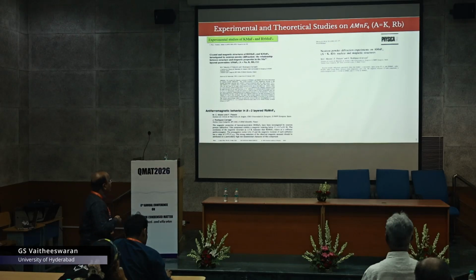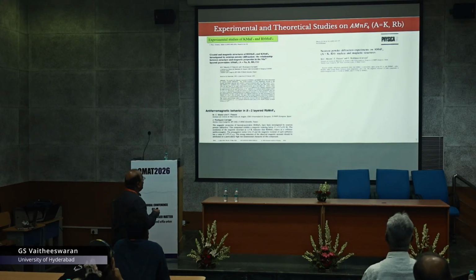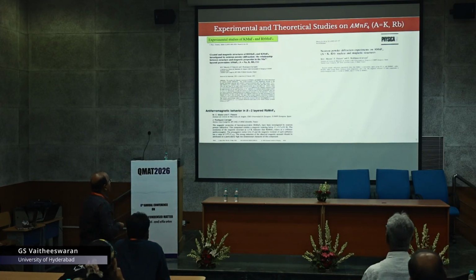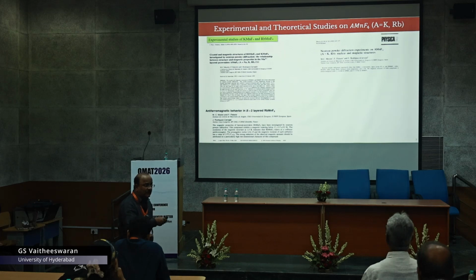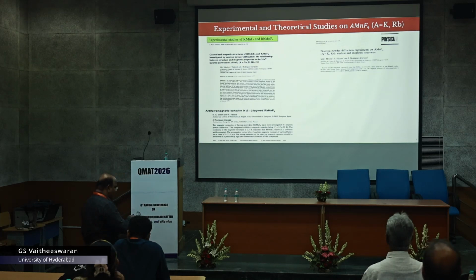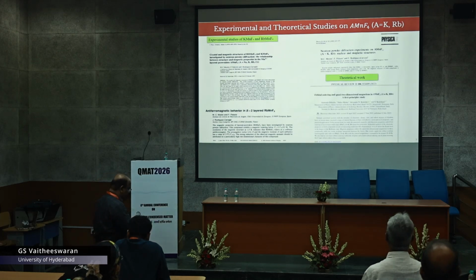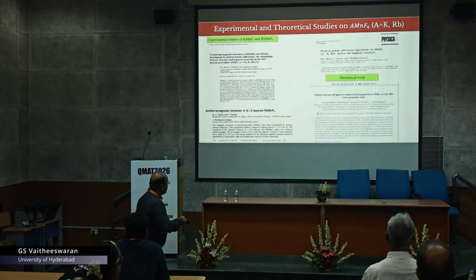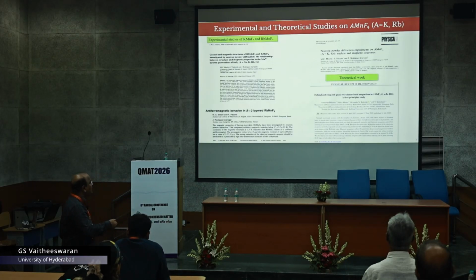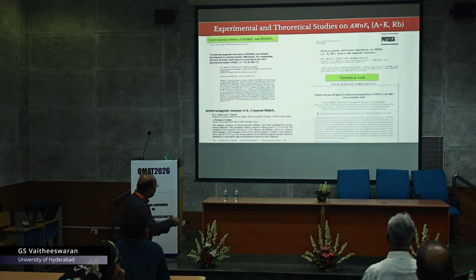Now let us start with the experimental literature already reported for the early alkali metal manganese fluorides. There are crystal structure details from X-ray as well as neutron data, and they tried to confirm the antiferromagnetic nature. There is also a theoretical work by Kanchana and co-workers from IIT Hyderabad, where they proposed orbital ordering as well as quasi two-dimensional magnetism in the potassium and rubidium based compounds. This is purely from first principles. So this is regarding potassium and rubidium.